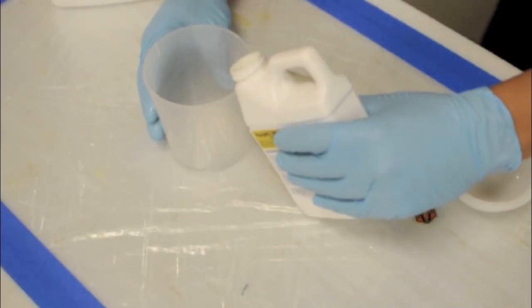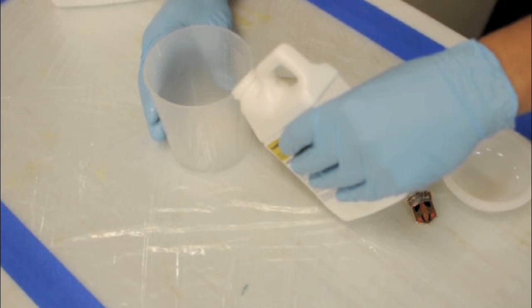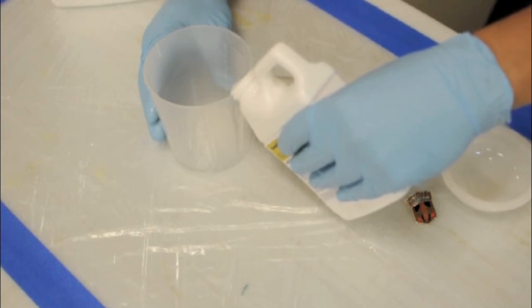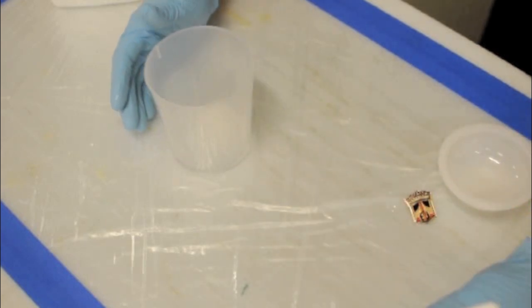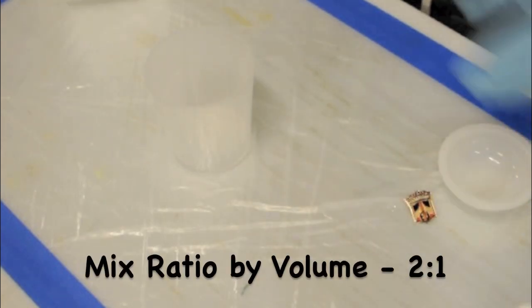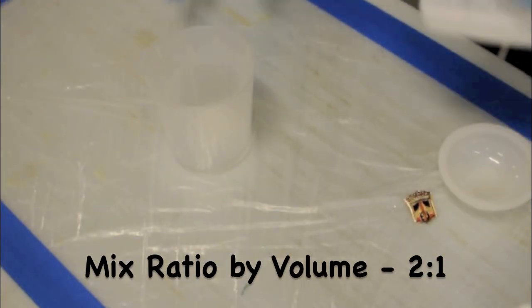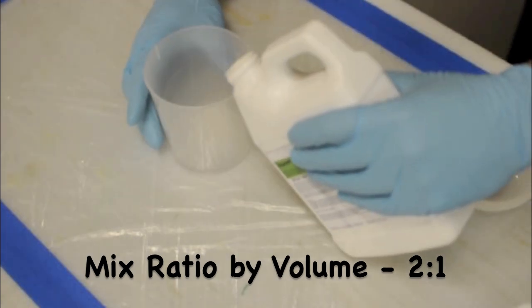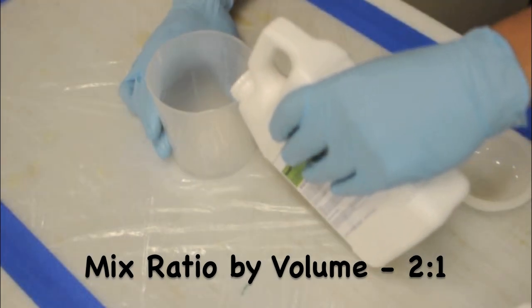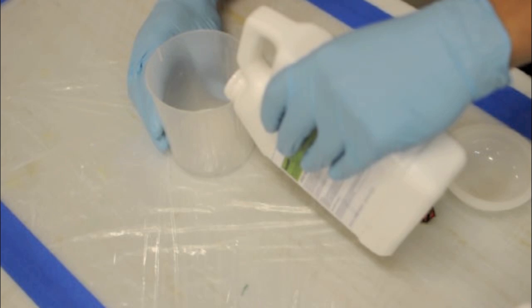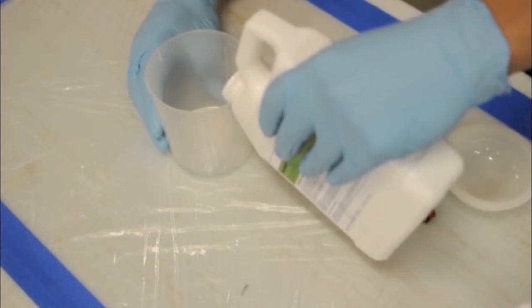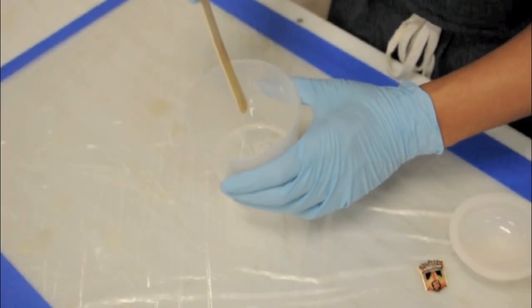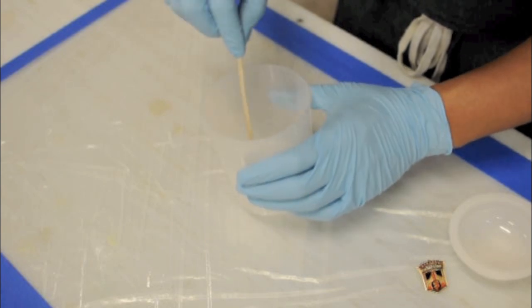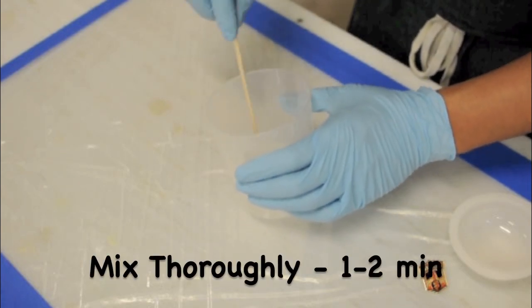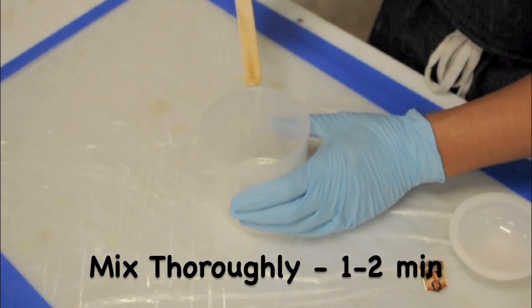First, we're going to start by measuring out and mixing our epoxies. All of our epoxies are two-part resins, which means an epoxy part and a hardener part must be mixed at the proper ratio. When doing small batches, it is often easier to measure by volume. And for ease of use, all of our retail systems are a 2-to-1 mix ratio by volume. Once you've properly measured out your two parts, be sure to mix them thoroughly, scraping the sides of your cups.